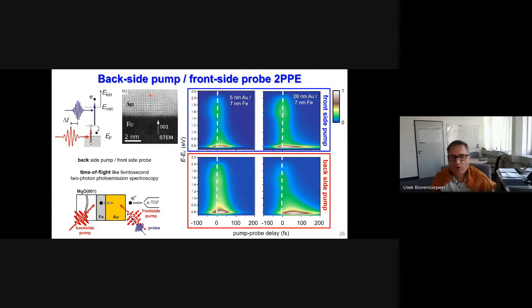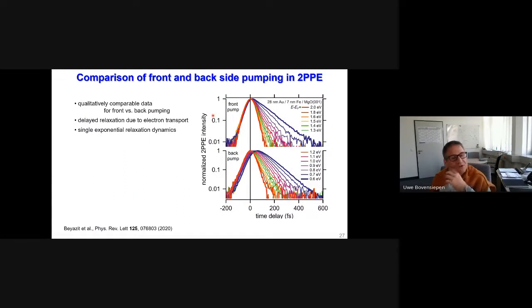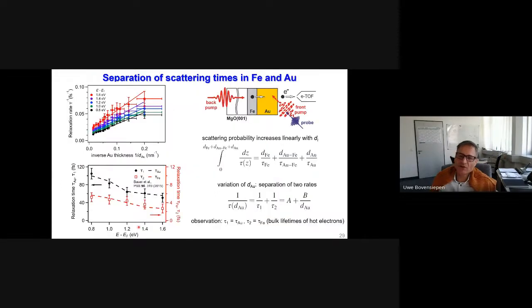But you make a very good point. If you consider that the interface is less perfect, then interface scattering would be important. This was also a point raised by the reviewers of our paper, and we have a very detailed response to that question in the supplemental material here. By varying both thicknesses, the iron and the gold layer thickness, you would be able to analyze this effect of the interface. It would be very interesting to compare to other systems. Thank you for the question.